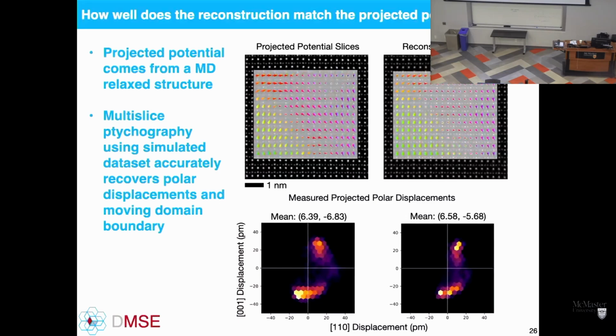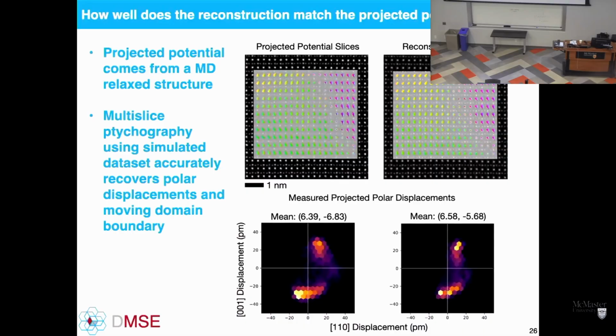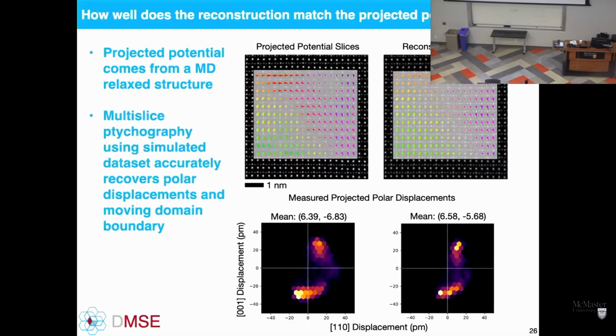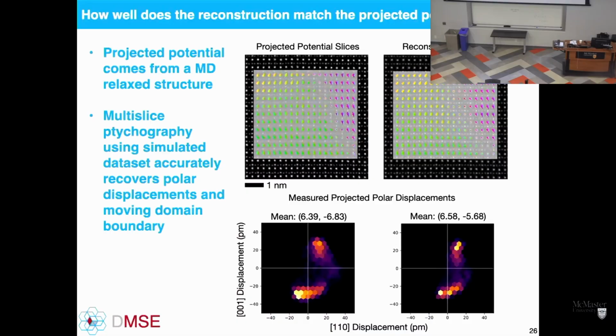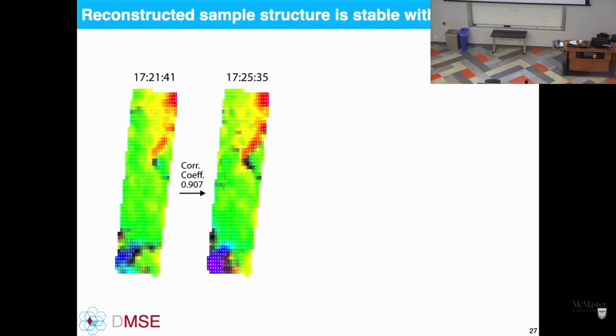So those measured projected displacements from the projected potential and the measured from the reconstructed, these are extremely close to one another. We're really measuring where those atoms are displacing with three-dimensional sensitivity. And more importantly, are we seeing something that's stable from one data set to the next? So we can go ahead and repeat the same measurement, the same 4D STEM data set acquisition over the same area, reconstruct it. These are just different timestamps.